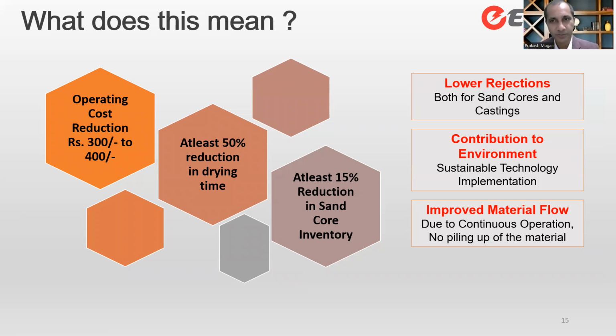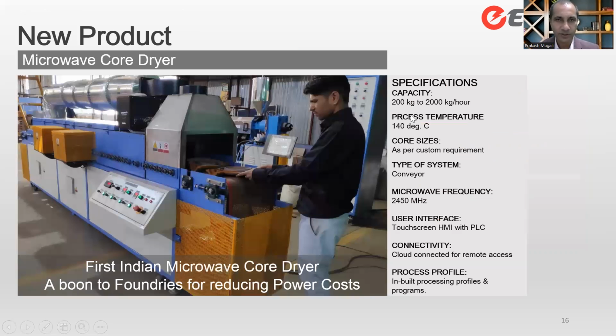Then we've seen lower rejections because the consistency of drying is a lot more. We are going with a continuous system with uniform drying, so the rejections are quite lower, both in the core itself and the castings that are produced with these cores. And the contribution to the environment, as I've already explained, is that it's a sustainable, green technology. We are talking about a 25 to 30% reduction in the energy consumption for the same unit of drying. On your shop floor, the material flows are much better due to continuous operation of the oven, and you can establish a material flow where no piling of the cores happens. In most batch processes, it does happen. Right? So these are some of the qualitative advantages of this technology.